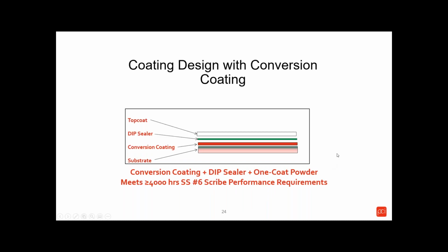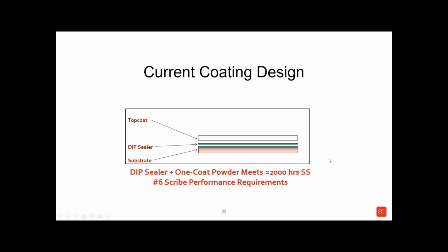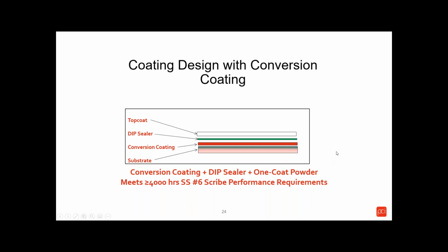And so we looked at option number one. Option number one was to first off, of course, look at the current method, and also look at an alternative, something that's maybe a little bit more robust, a little bit more performance, and give them a little bit more flexibility on materials used in the process. Same substrate, in this case, aluminum. The product was cleaned, and a conversion coating would be applied to improve its corrosion protection. A dried-in-place sealer was still being used, especially for stainless steel, to promote adhesion. And again, a single top coat would also be used as before. Now, this package would meet something greater than 4,000 hours, actually, on this aluminum substrate to the same scribe performance requirements.